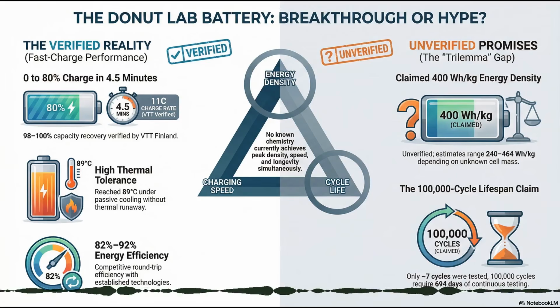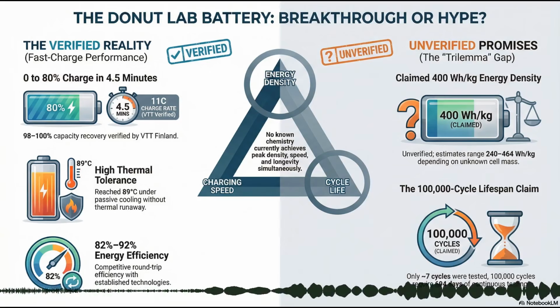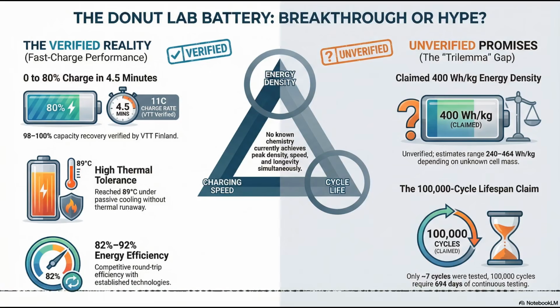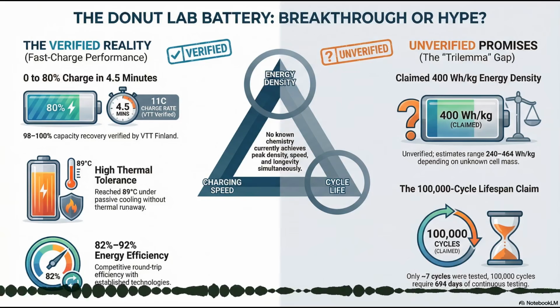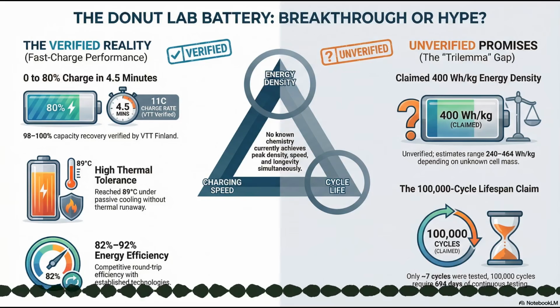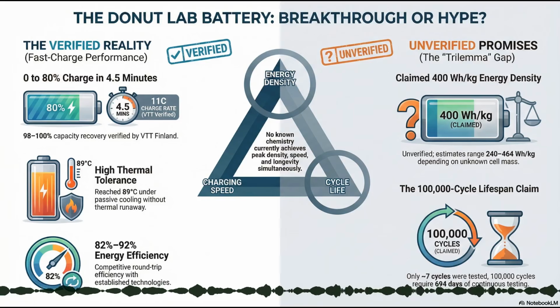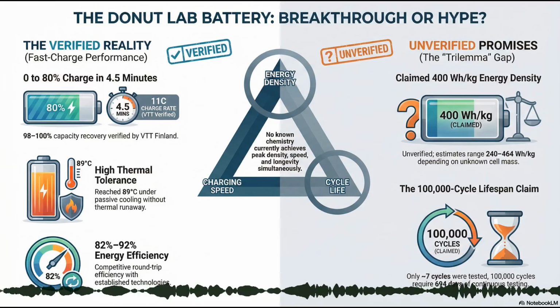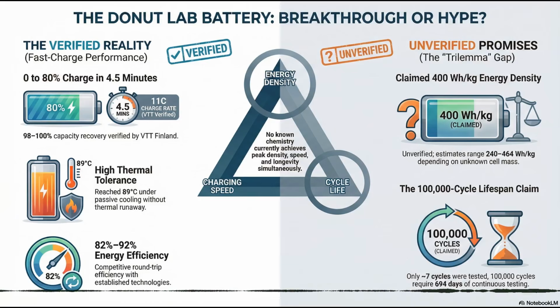The resistive heating raised the cell temperature, which lowered the impedance, which allowed the cell to accept that massive 11C rate without hitting the 4.3 V voltage cutoff too early. It's a self-optimizing system in a way. But as an engineer, isn't that living on the razor's edge? I mean, 90 degrees. Oh, it is a massive engineering critique I have of this system.